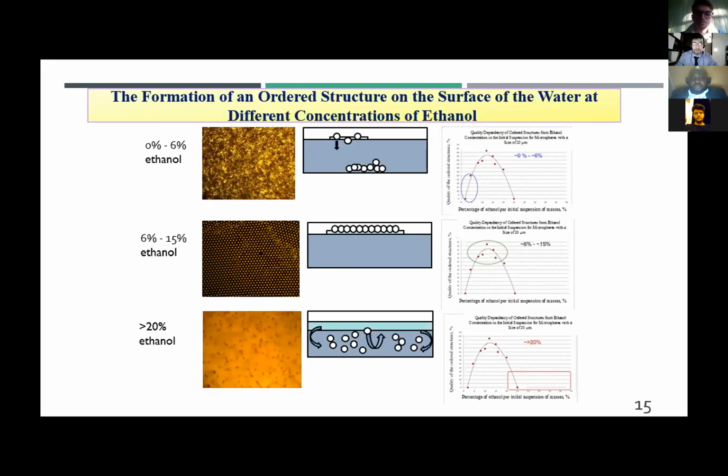The effect consists in a non-equilibrium flow of mass transfer of the dispersed phase, polymer microspheres, along the horizontal surface of the interface boundary of liquids. Due to Marangoni convection of the thin layer of matter, the microspheres are transported along the liquid phase boundary, forming a monolayer of microspheres. At the same time, the microspheres move in a vertical direction. Convection intensity can be controlled by changing the concentration of ethanol. The processes stop after evaporation of ethanol from the liquid interface. They can last for a fraction of a second.